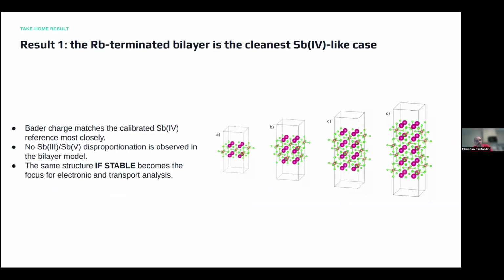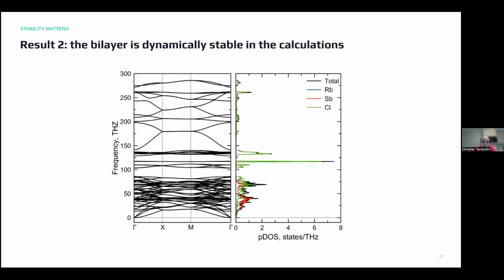So the first result that we got was that in this structure, with the bilayer and 3 layers, we have this antimony 4 stabilized. The most interesting for us is the bilayer, because the bilayer is the thinnest device that we could be able to produce. But to be sure that experimental people could synthesize it, we have to look at the stability of the bilayer.